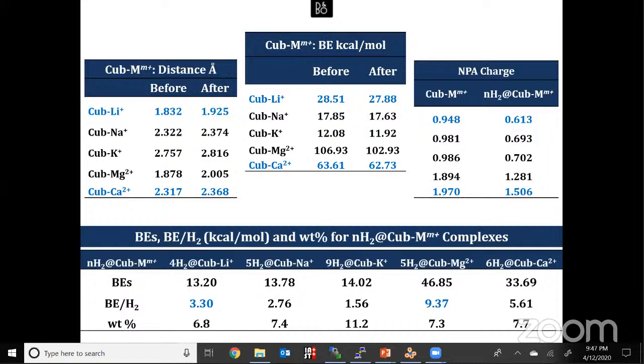Actually, what this metal environment is doing is polarizing the absorbed hydrogen molecule, but it's not totally polarizing. It's a little bit of polarization. That little change always makes chemists interested. That little bit of charge transfer traps the hydrogen molecule with the required binding energy per hydrogen molecule, and the low molecular weight substrate helps to increase the gravimetric density of the complex.